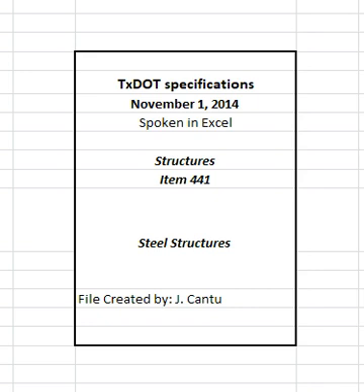3.2.6 Testing of galvanized weldments. If problems develop during galvanizing of welded material, the engineer may require a test of the compatibility of the combined galvanizing and welding procedures in accordance with this section and may require modification of one or both of the galvanizing and welding procedures. Prepare a test specimen with a minimum length of 12 inches using the same base material, with the same joint configuration, and using the welding procedure proposed for production work if testing is required.